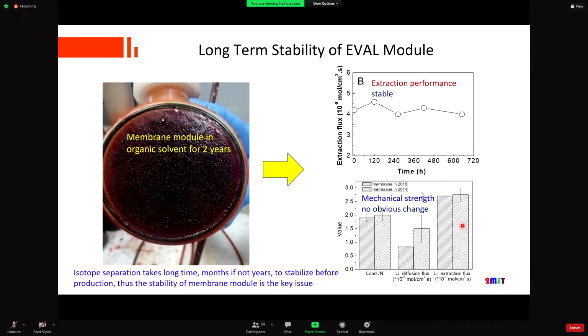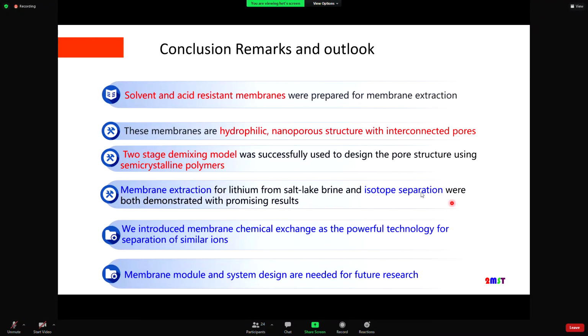We took the membrane sample out of this module and measured the flux and the mechanical strength. They are, especially the mechanical strength, surprisingly stable. So all the results come to one conclusion: EVAL membrane is a very excellent polymer for membrane chemical exchange. I'm not saying PEK membrane is not excellent - PEK membrane is certainly also a good polymer membrane for membrane chemical exchange.